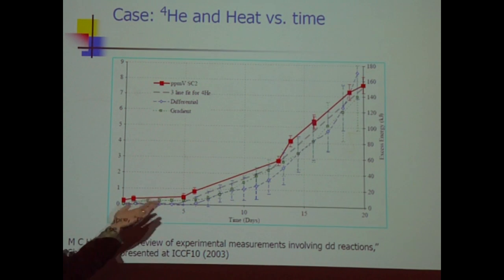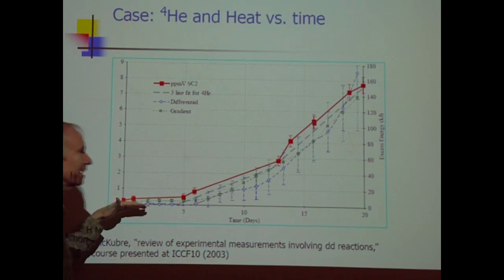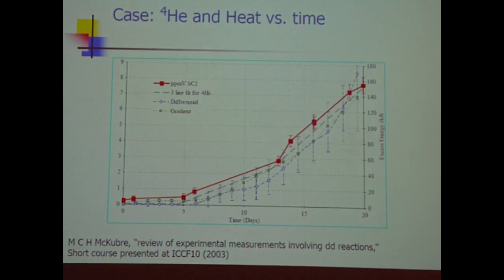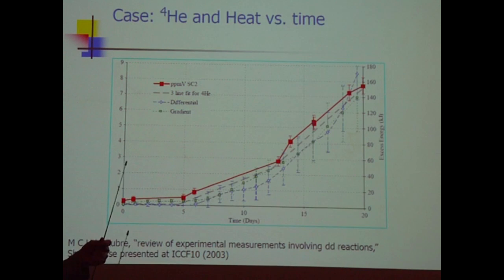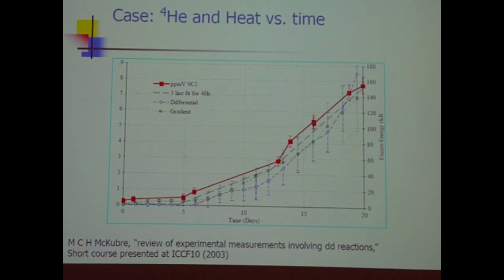So what you're supposed to look at and see here is that the energy production curve and the helium-4 production curve seem to match one another. I mean, you would prefer a differential of this, so if you get a heat burst, then you get a helium burst. Note that this measurement was done without the nice time resolution that Gozzi had for his system.